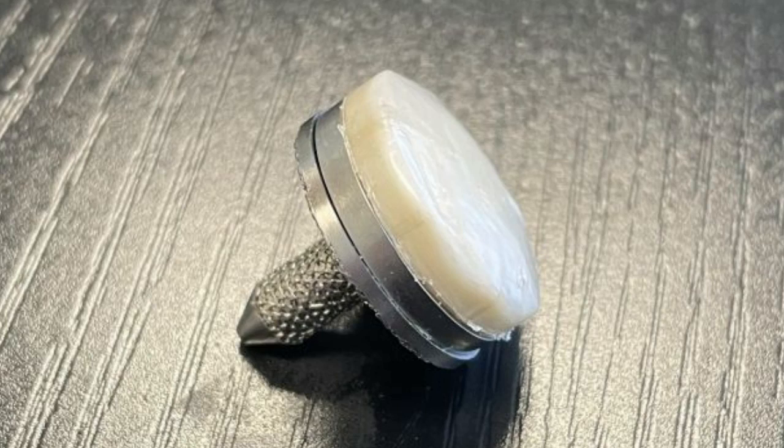Tests show the design stays fastened 68% more firmly than natural cartilage on bone. Another concern for knee implants is wear over time — both of the implant itself and the opposing cartilage. Other researchers have tried replacing damaged cartilage with knee implants made of metal or polyethylene, but because these materials are stiffer than cartilage, they can shave against other parts of the knee. In wear tests, the researchers spun artificial cartilage and natural cartilage against each other a million times at pressures similar to walking. Using a high-resolution X-ray scanning technique called microcomputed tomography, the scientists found that the surface of their lab-made version held up three times better than the real thing — and because the hydrogel mimics the smooth, slippery, cushiony nature of real cartilage, it protects other joint surfaces from friction.